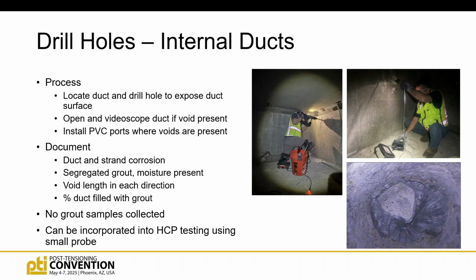We look for segregated grout and document that. We try to measure if there's moisture present and what that percentage might be if we suspect moisture is there. In many cases, there's not moisture there, so we don't do that testing. We check void length, and then I have our folks estimate the percent of the duct that's filled with grout. And so the length and the percent filled helps us define what the volume could be, right? So that when we're doing repairs, we can back check that.